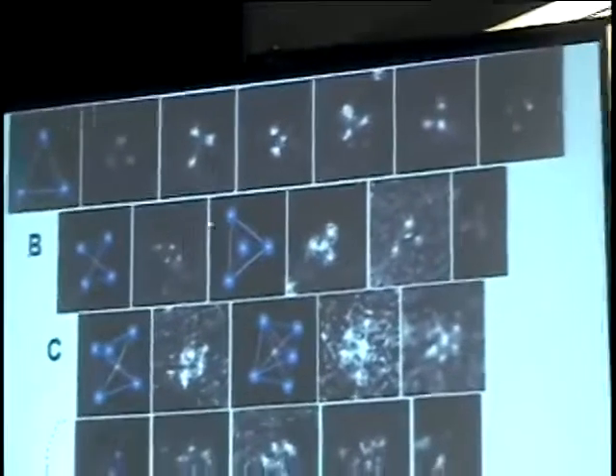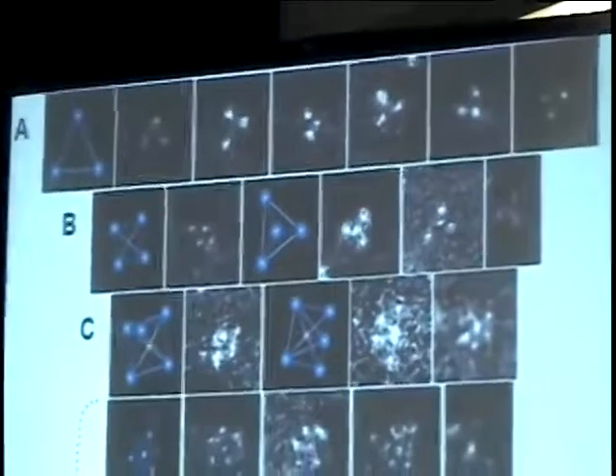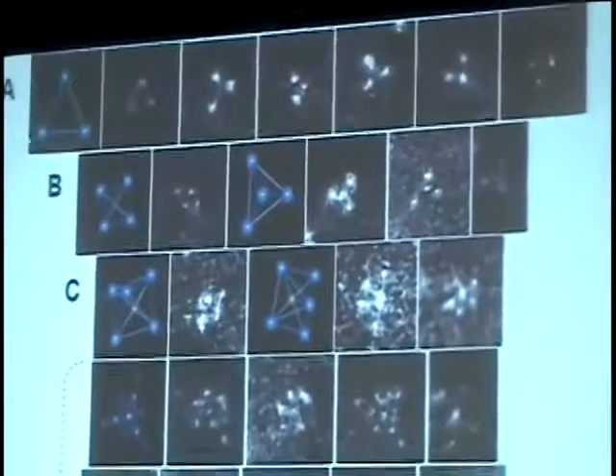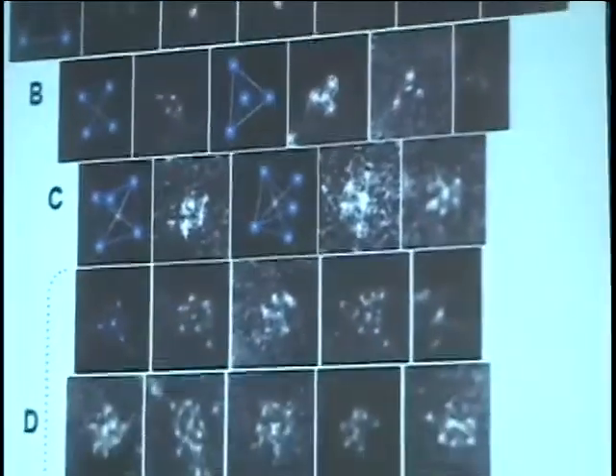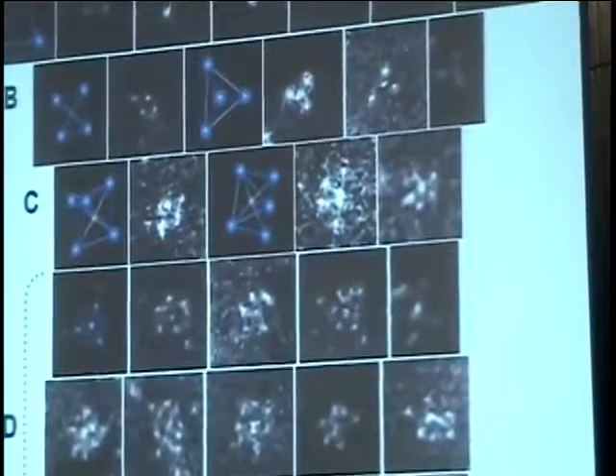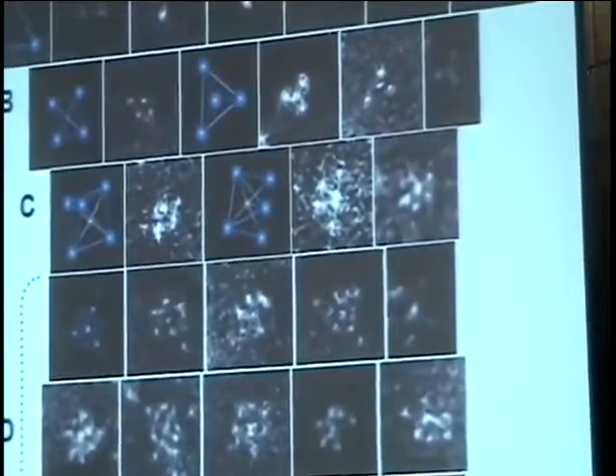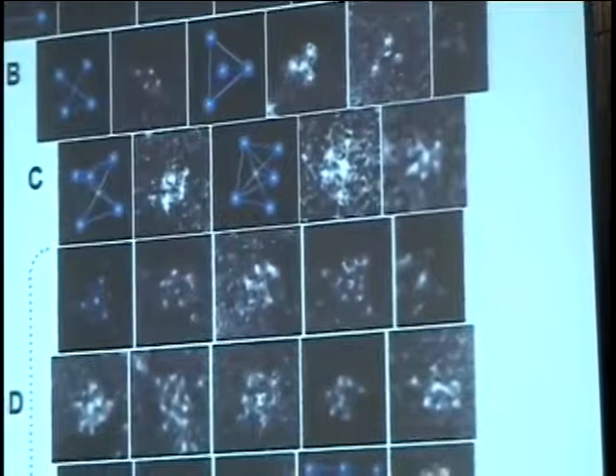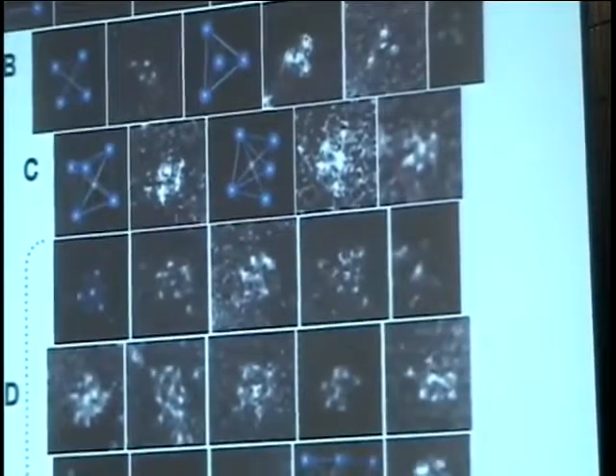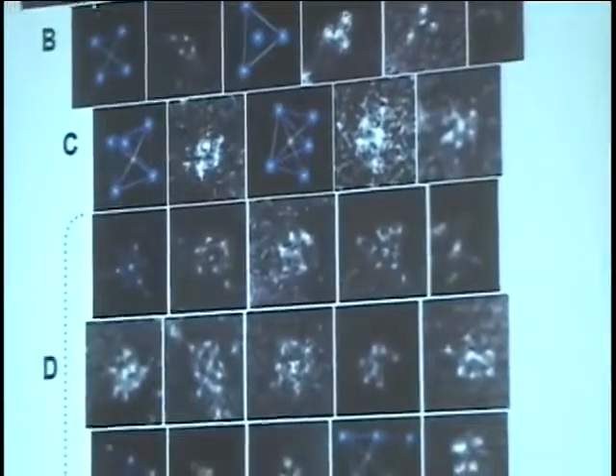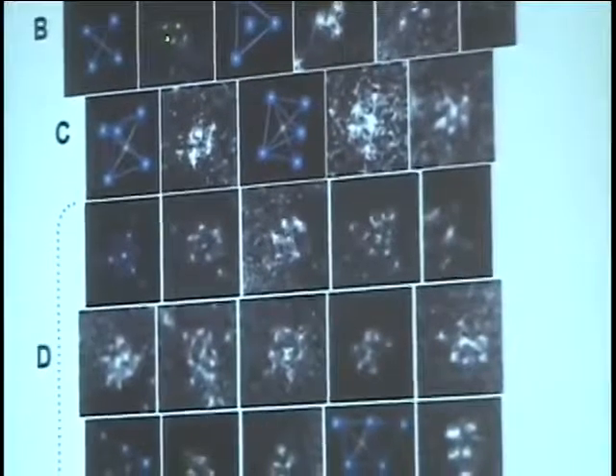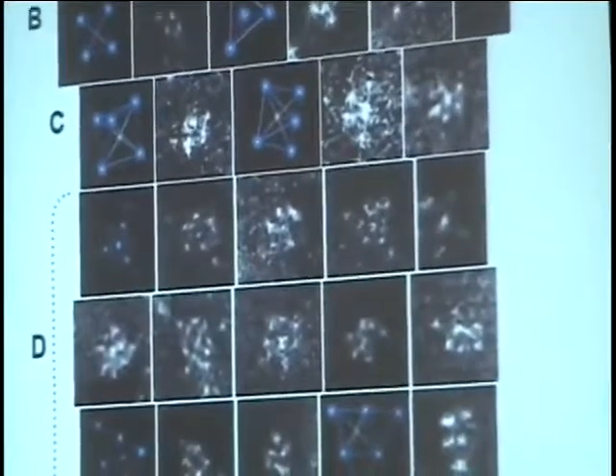So what do we see? Well, what we see is what we've seen. So here are triangular species. I'm putting the framework structures in that kind of blue-gray. So here's the triosmium, and here are a number of images in which we see triosmium, and I don't think one would dispute that those are really triosmium. And then beyond that, tetra. So here, 4-atom cluster, here, 4-atom cluster, and so forth.